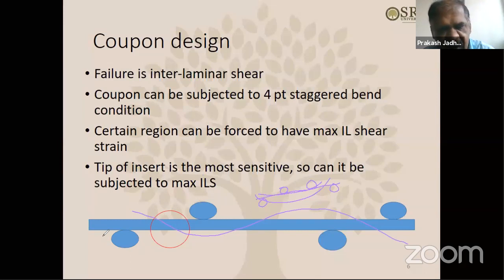So what are we achieving by using this staggered 4-point bend is, using the analysis, we compared the regular 4-point bend and the staggered 4-point bend. And we found that in this particular region inside the circle highlighted here, the interlaminar shear strains were very high. So basically, it's like forcing the coupon to have a maximum interlaminar shear strain in a certain region. So this is what we did and decided to use this design.